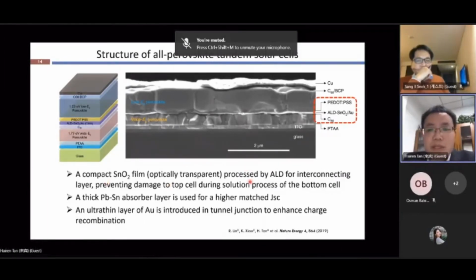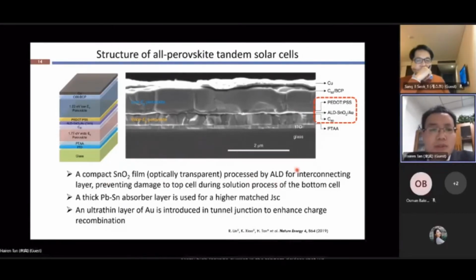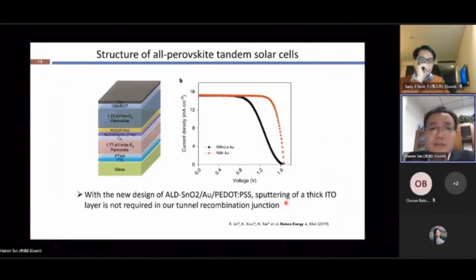So what we do is we use the atomic layer deposition approach to deposit a very compact tin oxide film, and that is around 20 nanometers thickness. Use a very thick absorber layer for this layer so that we can get a higher matched current density. But this is not enough. We found that if we directly deposit PEDOT on top of the tin oxide layer, the fill factor of the tandem devices is quite low. So we suspect that this may be due to inefficient charge recombination between the two subcells.